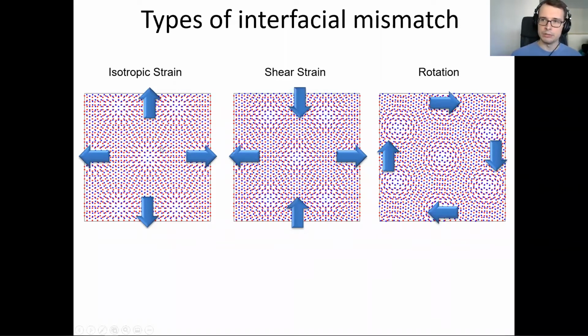Now, isotropic strains still can be used. In 2013, there was a series of experiments at various groups that studied how if you put graphene on top of hexagonal boron nitride, the small lattice mismatch creates a Moiré pattern that looks like this sort of strain Moiré pattern. And this was used to show the Hofstadter butterfly effect on this emergent superlattice. Because now the length scales are so long, you can use experimentally achievable magnetic fields to see the fractal filling of the Landau spectrum. Okay.